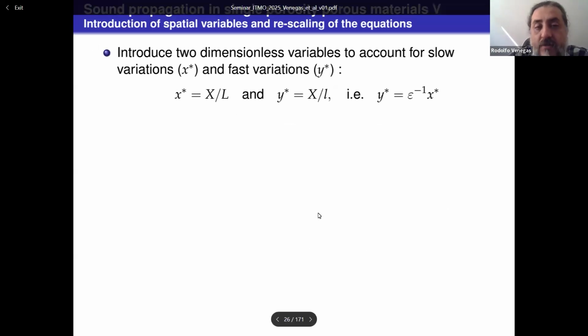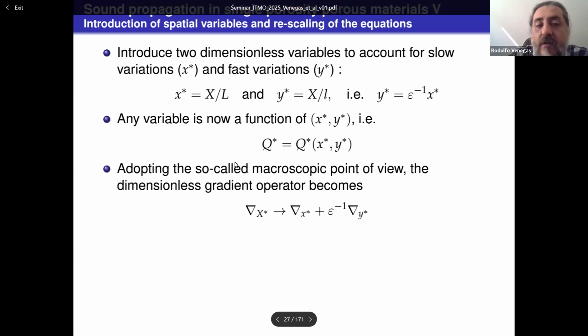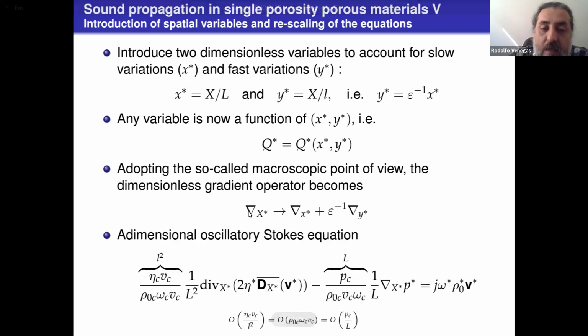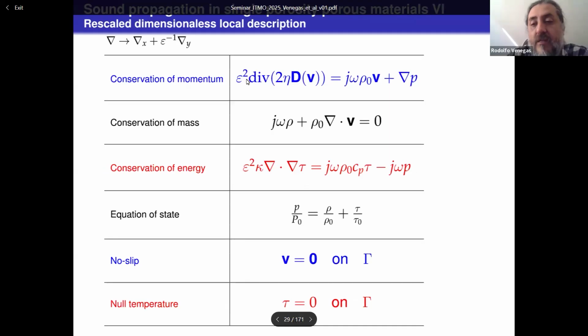Using that, we introduce these two adimensional spatial variables, accounting for slow variations and fast variations. Now, a priori, every variable is a function of these two spatial variables, and as a consequence, because these are independent variables, we can write the gradient operator in this way. It becomes essentially a function of two variables, so we use this for the Nabla operator. And we insert this, adimensionalize the Stokes equation, and we identify that this term is in the order of l squared divided by big L squared, so that's in the order of epsilon squared, and this is what appears here as a rescaled local equation of conservation of momentum.